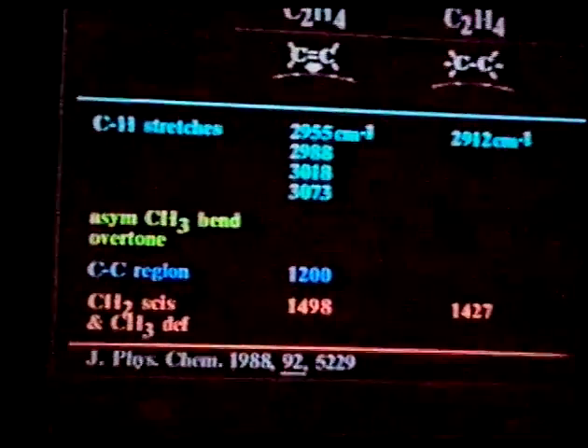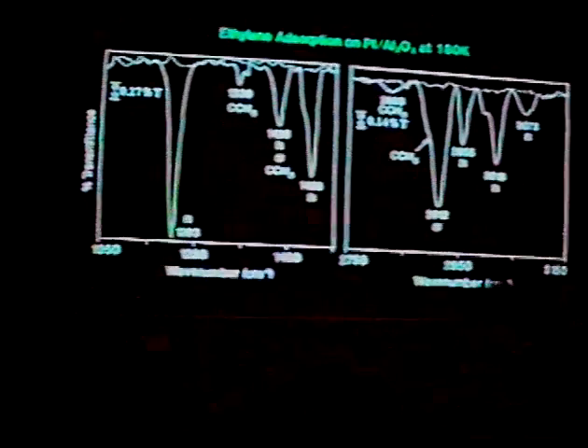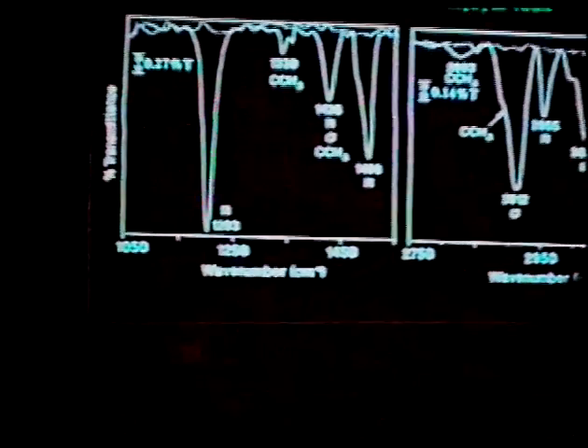But the problem is that for most supports, alumina, silica, zeolites, when you get down below about 1,000 wave numbers, things get very, very dark on you in a hurry, and you lose those bands. So the way in which we're going to be identifying these species is on the basis of these assignments. And I'll show you here what such a spectrum looks like.